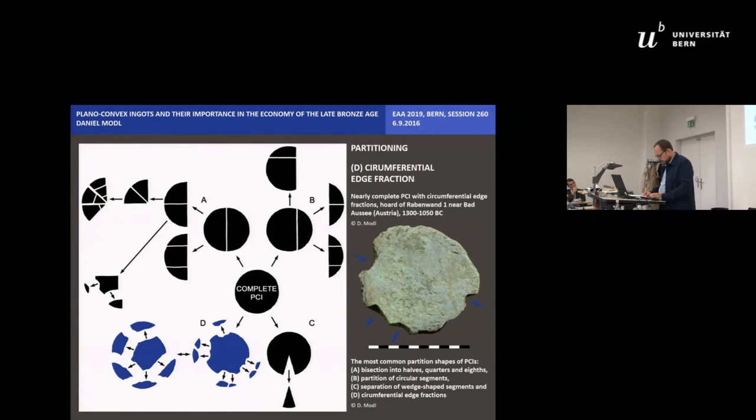Let me say here some words about the metal composition of the PCIs and what that means for the practical work with them. Metal analysis of Bronze Age PCIs in Central Europe revealed that they are originally made of chalcopyrite copper, fahlerz copper or less commonly, a mixture of both types. As changeable copper contents and varying amounts of minor elements like arsenic, antimony and nickel or iron show and also impure, partly refined as well as nearly pure and even alloyed copper were used for their production.